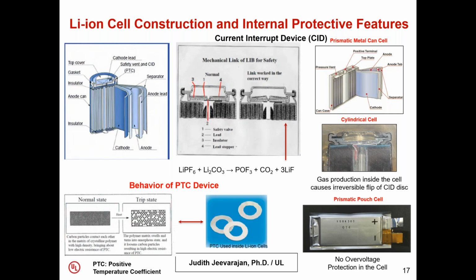The prismatic pouch cell is protected mostly against a hard external short, which is a low impedance short. The way this is done is that one of the tabs, the one which has a lower melting point, burns off when you have a hard short on the cell. At this point, the cell is in a fail-safe mode, because you cannot charge or discharge it since the tab has burned off. I have seen in very rare cases a circuit board that is attached between the tabs of the pouch format cell in its application, and this circuit board can be placed physically on the cell itself. In those cases it provides protection against overvoltage and undervoltage as well as overcurrent. But in the picture that I show here, that is not available.